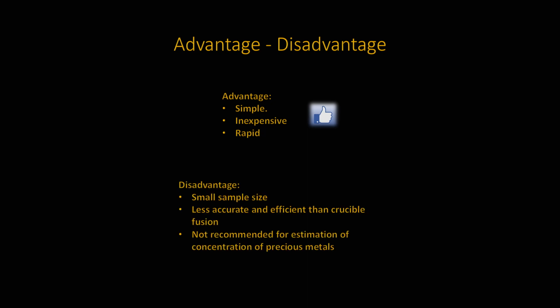Smaller sample sizes make this process less efficient as sample size is restricted. This also makes it less accurate for concentration determination of your source material. Therefore, it is not recommended for the estimation of concentration of precious metals. It is mainly used for the pre-collection and refinement of the precious metals in small-scale samples, usually used for discovery, and lead button treatment of beads from crucible fusions.